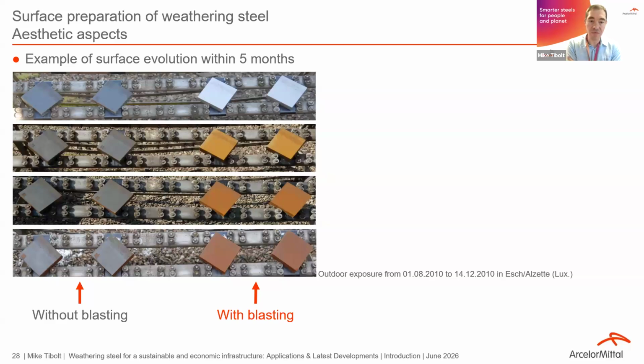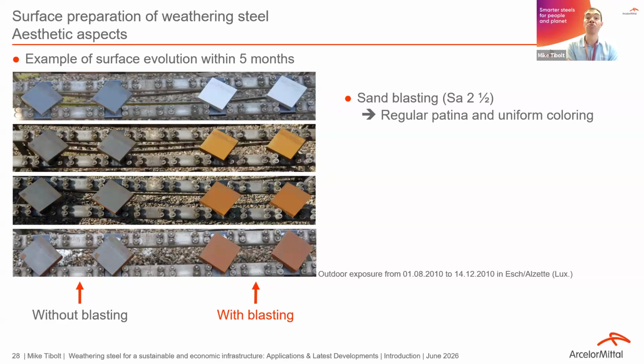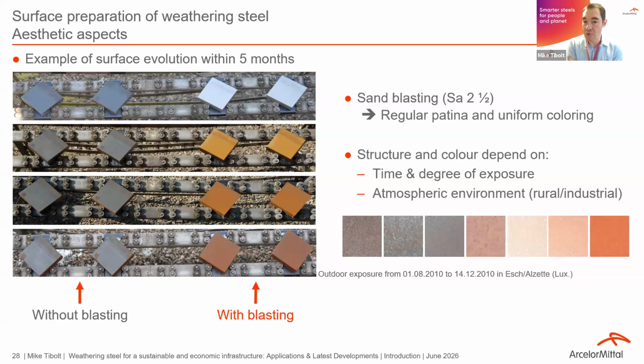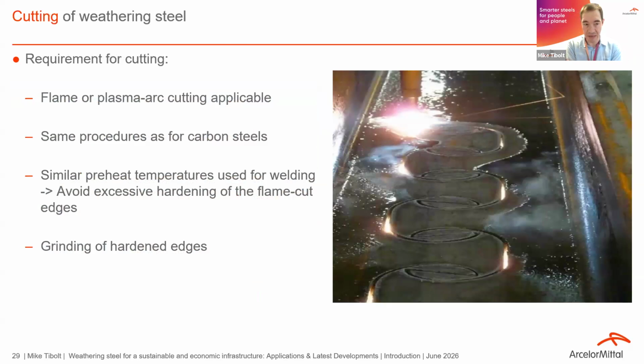The fabrication. First of all, here you see the example of surface evolution within 5 months, without blasting and with shot blasting. We see that with shot blasting we get a much more homogeneous coloring of the surface. That's why we always advise to use sandblasting Sa 2.5, to have a regular patina and a uniform coloring. At the same time, the coloring will depend on the atmospheric environment and the time and degree of exposure. So it is not really controllable in every detail. It depends on the time and on the environment finally.